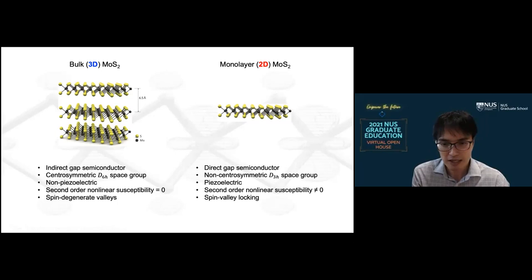And one of the most important aspects of going from three-dimensional to two-dimensional structure is that this effect of Coulomb screening is very different. In the three-dimensional world, screening is very strong, whereas screening is very weak in the two-dimensional world. What is interesting is that just simply changing the dimensionality of a material without touching, without altering their chemistry, meaning that the chemistry is exactly the same, by changing the dimensionality, a whole new set of properties start to emerge. And again, this weak screening is one of the most important attributes of a two-dimensional molybdenum disulfide.